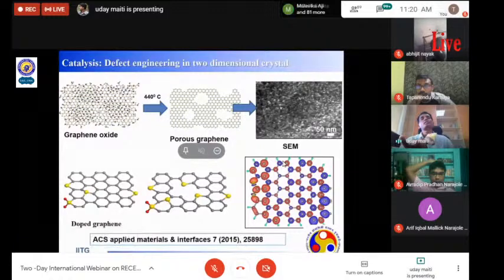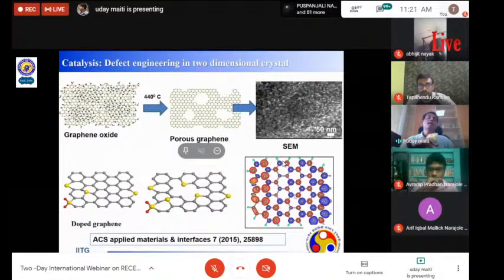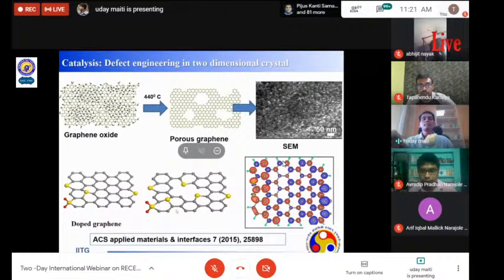And once we create the holes, it is easy to dope with the bigger heteroatoms. We have doped with sulfur, and those sulfurs are mostly incorporated near these pores, because we have confirmed from the XPS the configurations of these sulfurs. And we have also done density functional theory simulation. From that, we have found that due to this heteroatom doping, there is a redistribution of electrons and spin around some atoms around the edges. So this redistribution, localization of electrons has some impact on the catalysis. We used it for the oxygen reduction reaction catalysis. If you would like to have more detail, please go to this publication.